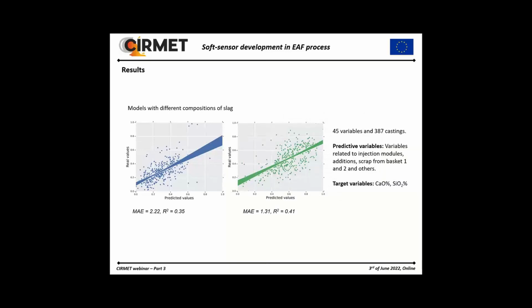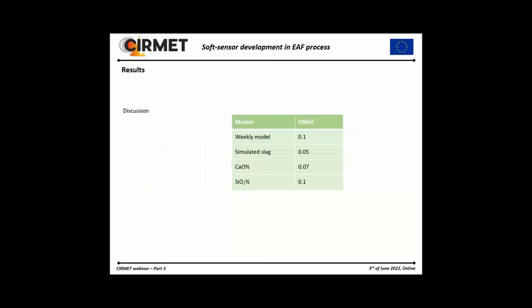And finally, here we have the different composition of the slag, the lime percentage and the silicon oxide percentage. Here we used the same number of castings as in the previous case, and also 45 variables. In this case, we used also the random forest regressor and the 5-fold cross validation. So here you can see for the two methods, the MAE and the determination coefficient of the two models.